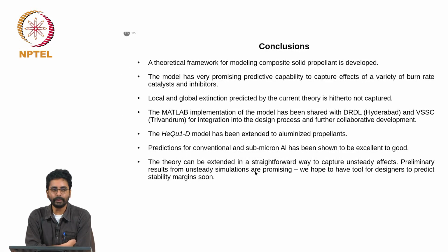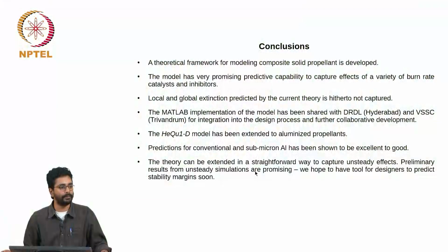Yeah. There are two questions. What is the typical percentage of aluminum particles for agglomeration? Does it depend only on the percentage, or does it also depend on the surface temperature? Well, it depends on the percentage, it depends on the size, it depends on the number density, and it may also depend on the temperature. But the fraction and the size effect seem to be the most important, because close to the surface temperatures are roughly the same, about 1200 kelvins.